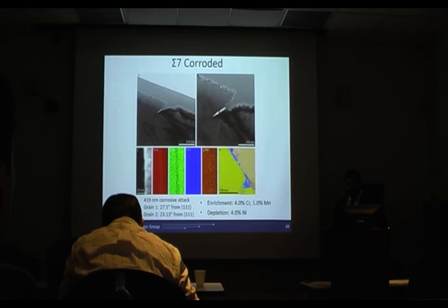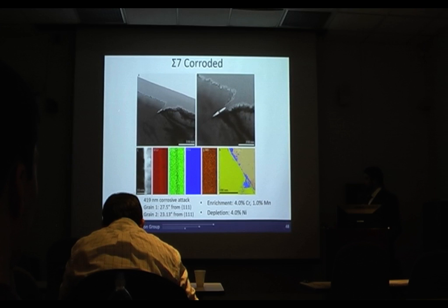When we lifted out the one that corroded, there was again over 400 nanometers of corrosive attack, which you can see here. Both grains are over 20 degrees away from a 111, and we have enrichment of 4% chromium and 1% manganese, and then depletion of nickel this time instead of iron.